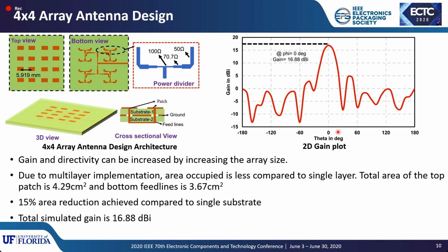And also from the 2D gain plot, you can see that the simulated gain of this architecture at 28 GHz is close to 16.88 dB. So based on these simulation results, we try to fabricate the antennas on the glass substrate.